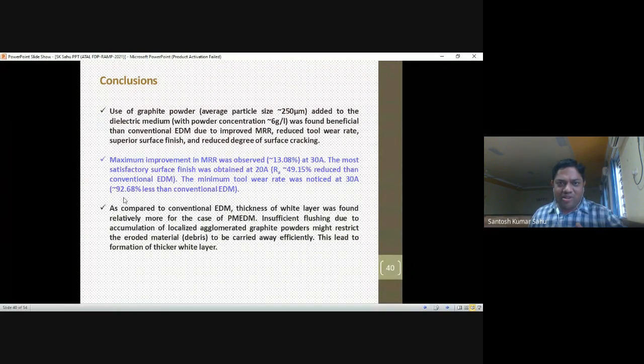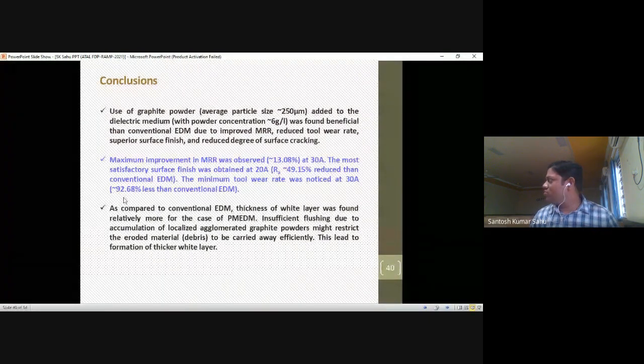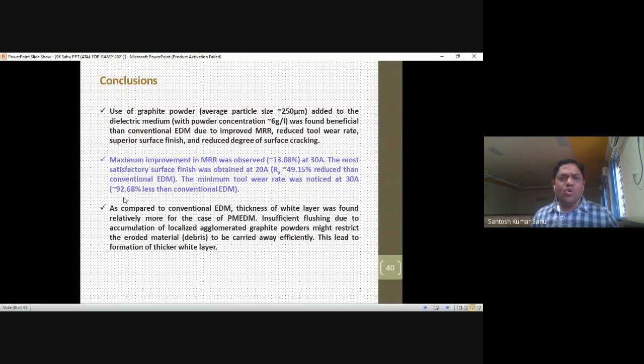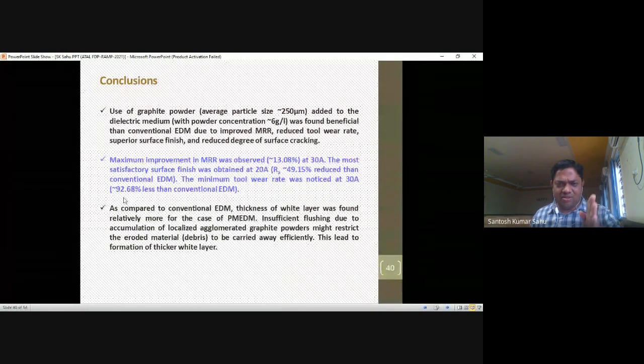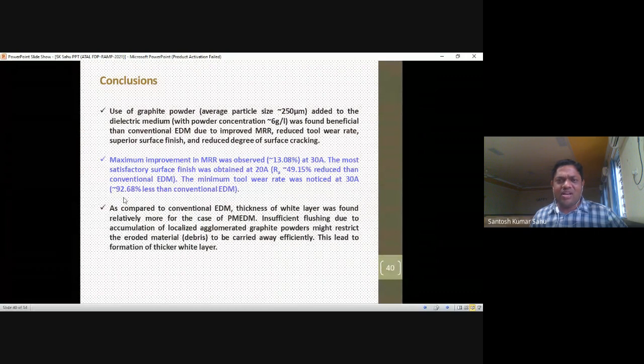So the use of graphite powder at an average size of 60 mesh, or 250 microns, added to the dielectric media at a constant powder concentration of 6 gram per liter, is found beneficial over conventional EDM due to improved MRR, reduced tool wear rate, superior surface finish, and reduced degree of surface cracking. Again, we can conclude that the maximum improvement in MRR was observed at 30 ampere. A more satisfactory surface finish we can get when the current is 20 ampere, and the minimum tool wear we can get when the current is 30 ampere.